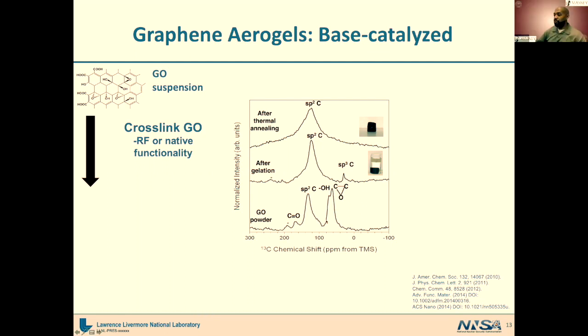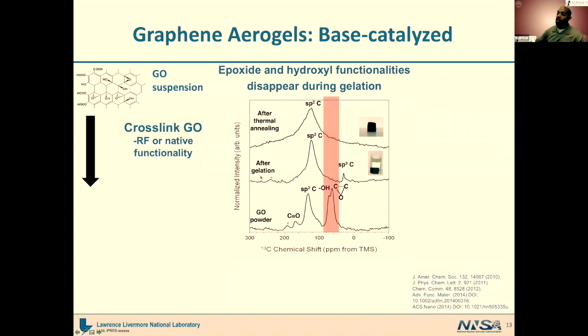So what we can do is use that resorcinol formaldehyde chemistry and couple that with the functionality, or actually just use the functionality by itself at a high enough concentration of GO to form our gel. Here we're following, using NMR, what's going on, starting off with your GO powder, which you put into liquid. You would add in a base catalyst. And what you would find, if you did NMR on this gel, is that you have removed the epoxide and hydroxyl functionalities.